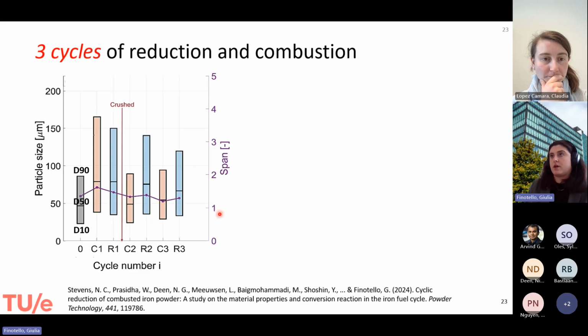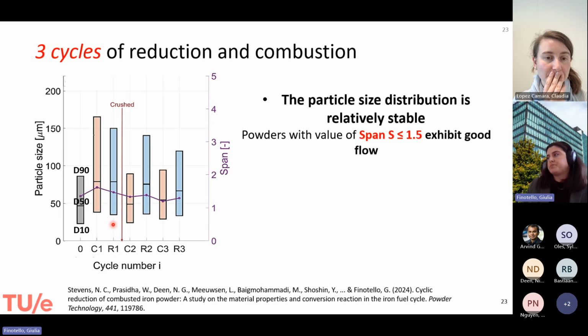So we did this. We did first 3 cycles of reduction and combustion, and here you can see only part of the result. You can see the particle size. This is the initial particle from where we started, and then we did a cycle of combustion and reduction. So C1 is the first cycle of combustion, first cycle of reduction, and so on. And indeed, we see that there are changes. Of course, there is agglomeration in both combustion and reduction. However, it is still an acceptable distribution, because if we calculate the span, this is lower than 1.5, which is related to relatively acceptable flowability.